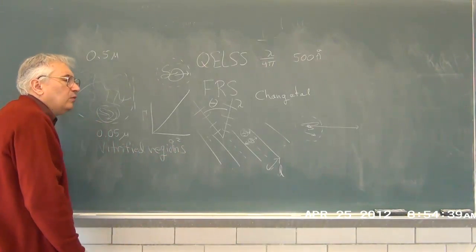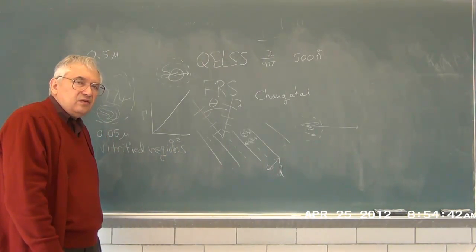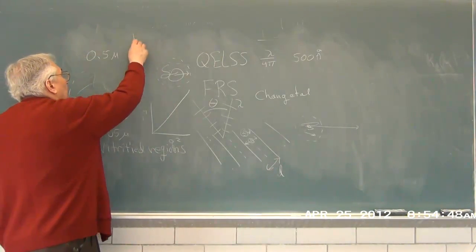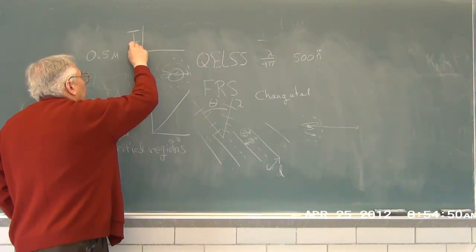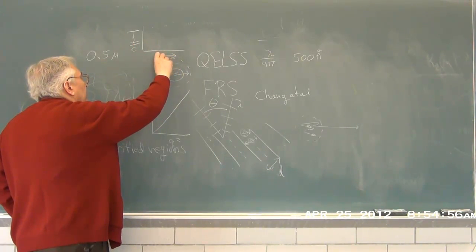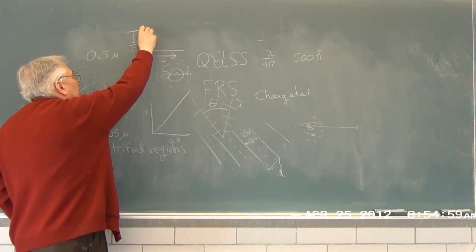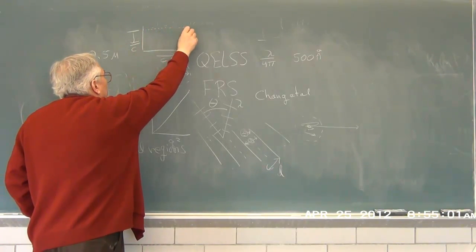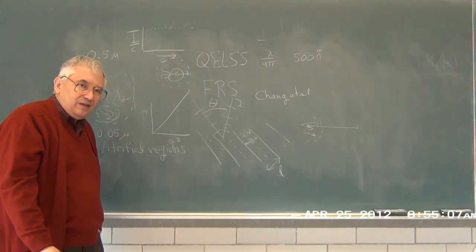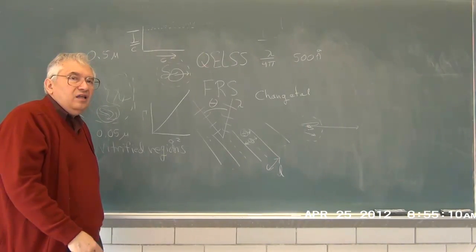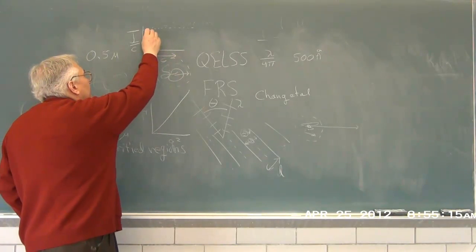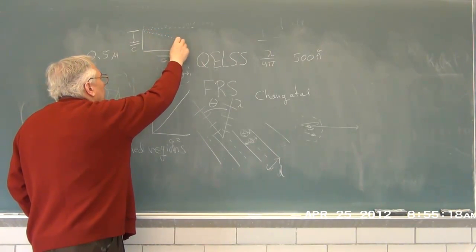Well, we actually don't know. One thing we can say is that they're not local regions of high or low concentration. Why? Because Rob O'Connell measured the intensity. We'll plot it as intensity over concentration versus concentration. If you simply had objects that didn't interfere or anything, the intensity would be constant. If the objects repel each other, which is typically the case because they can't move through each other, as you make them more concentrated, it gets harder to form a concentration fluctuation, and the intensity therefore falls.